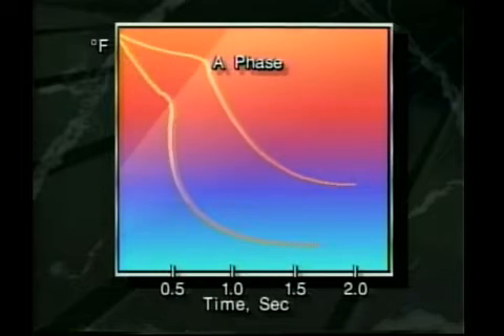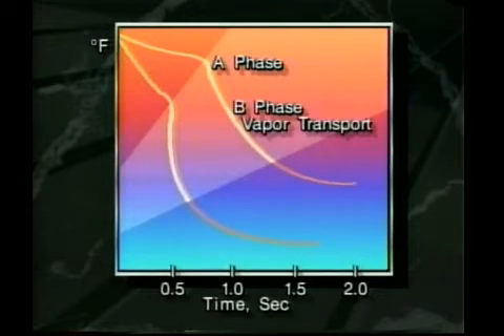2, the vapor transport phase, the B phase. During the second stage of cooling, the vapor film has completely collapsed, and there is rapid heat transfer along with violent boiling as continual fresh, cool liquid contacts the surface of the part. During this B phase of cooling, actual quenching of the component takes place, and it is in this phase where control of the rate of quench for achieving properties is necessary.